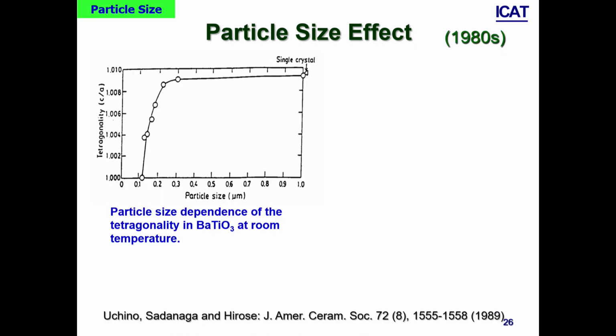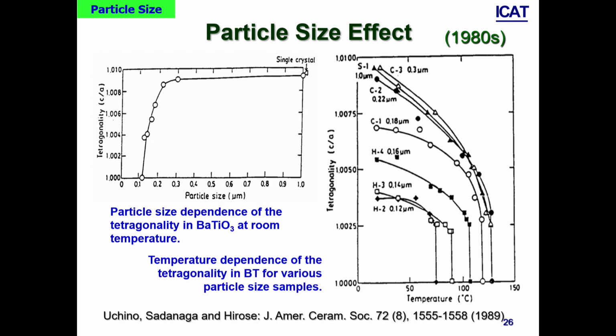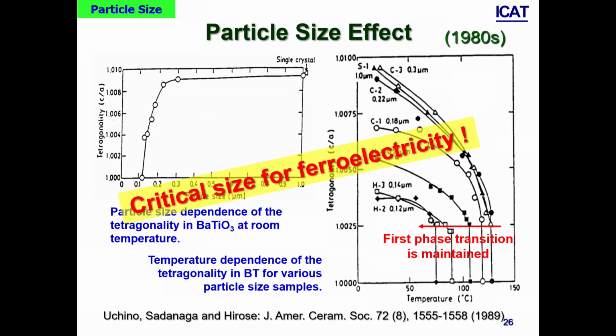That is a risk to this particle size dependence of barium titanate. So with reducing particle size in barium titanate, actually in the middle of the 80s, sol-gel or alkoxide fine particle technology was arriving. So we started to use these small particles. We found that the tetragonality is just gradually shifting to lower temperature without changing, and the first-order phase transition, the drastic change, is maintained even for small particle size. So basically, smaller particle size creates some hydrostatic pressure that reduces the Curie temperature. That's our speculation. Critical size for ferroelectricity.